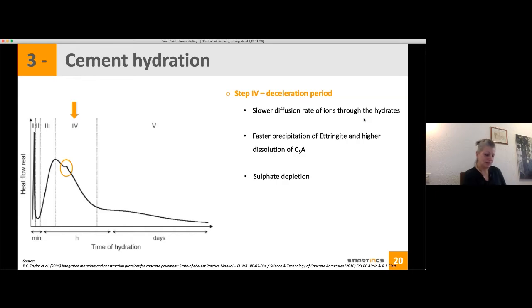What happens, I said in step 1, you have hydration of C3A to have some ettringite. So it's immediate, but then it stops. And here you will see a renewed hydration of your C3A because you still have some sulfate present and some C3A. So this is what you see with a peak with a shoulder. And this reaction will take place as long as you have sulfate. And when you don't have sulfate anymore, then you cannot have ettringite formation anymore.